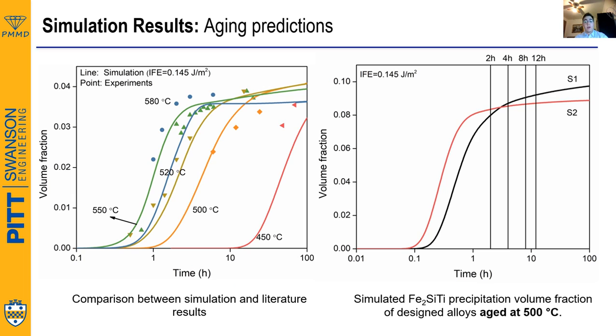Furthermore, in order to define the aging time to study, an aging model was developed. The main parameter for this model is the interfacial free energy. So using information from the aging behavior of the L21 phase in the iron titanium silicon system, our model was calibrated, and the best fit for the interfacial free energy was set to be the constant value of 145 millijoules per meter squared. This best fit is shown in the left figure here. This figure shows the overlapping of the L21 aging behavior reported in literature in the context of the iron titanium silicon system, and the corresponding simulation predictions of our model.